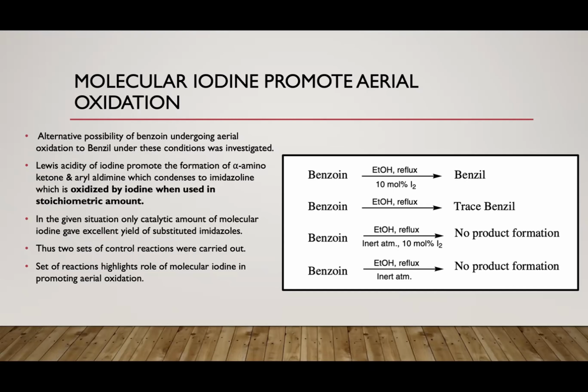Looking at the literature data, we found certain papers which show that iodine is capable of carrying out the conversion of benzoin to benzil, but that too in stoichiometric amount. And in our synthesis, we were able to reduce the amount. We were using it in the catalytic amount. So that was the improvement which we did in the synthesis.